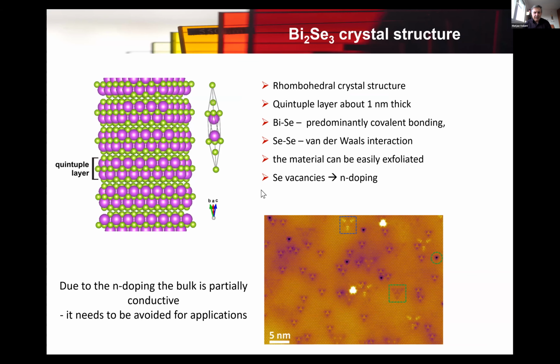and the other thing shown in this picture is the fact that when you grow this material, they often contain a lot of structural defects, which cause some kind of conductivity in the bulk, and then you don't have a pure, proper topological insulator anymore. And this is another topic. I'm not going to talk about this today, but it's another problem with these materials which still needs to be worked out.